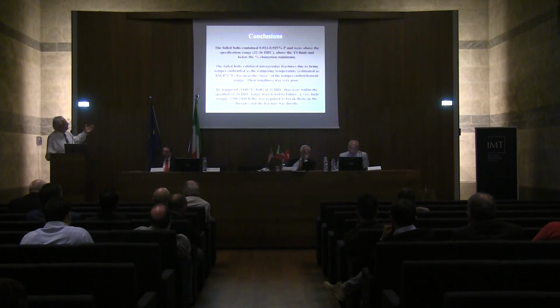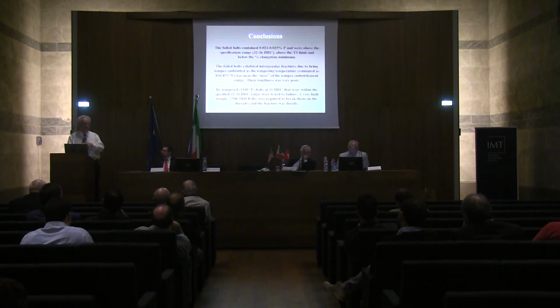They had a very high torque, 2,500 to 2,800 foot-pounds required to break them. And the fracture was ductile. One of my buddies at Bethlehem Steel and we took a bolt that had never been in service and we tempered it back. It was high hardness to begin with, but it was never used. We tempered it back to 35 Rockwell C,